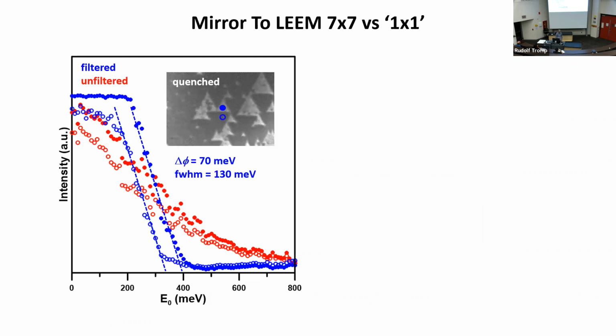Let's first see. So here I do an experiment which you call a mirror-to-LEEM experiment. Initially, the sample potential is more negative than the electron gun. So the electrons come to the sample, they slow down, and then they find that the sample is more negative than the electrons are fast, right? So they turn around in front of the sample, they never touch the sample. Then when I slowly make the sample potential more positive, the electrons come closer and closer. At some point, they hit the sample. And when they hit the sample, the reflectivity changes from 1 to something smaller than 1.